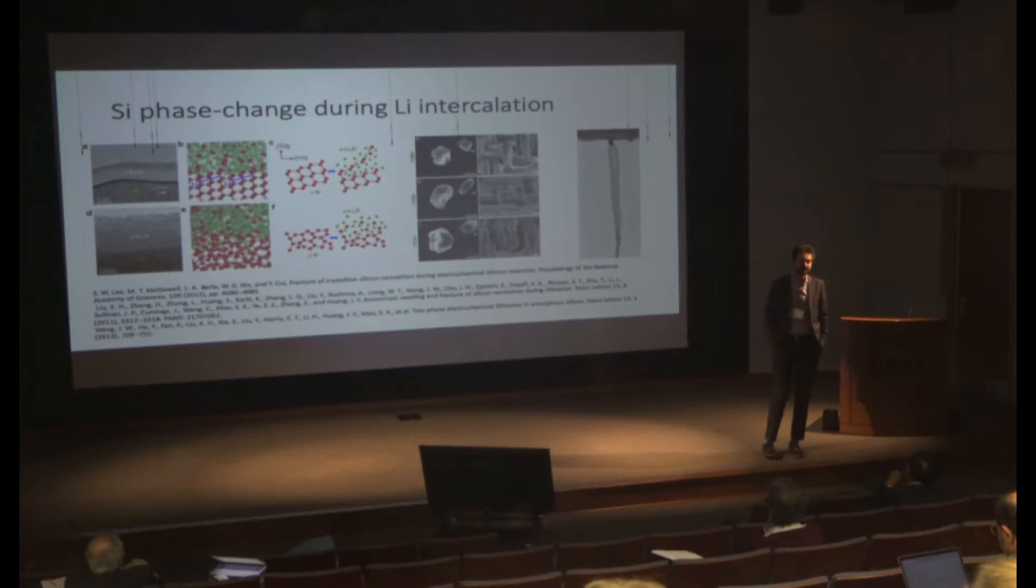When you push them to their theoretical capacity, if you start from crystalline silicon, as the lithium invades it disrupts the covalent bonds and makes the crystalline structure amorphous.